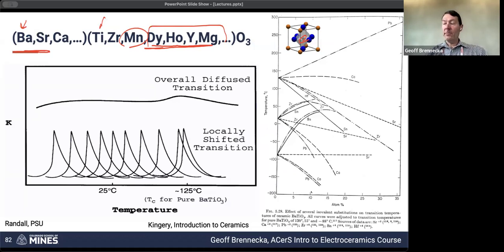And holmium and dysprosium happen to be right about in the middle. They're just as happy being in the A site or the B site, and so they can end up being self-compensating. If your sample has too many oxygen vacancies and needs to compensate for that, then maybe the holmium and dysprosium will hang out on the B site. If you've gotten your A site to B site ratios just a little bit off, these kinds of dopants can help compensate for that a little bit. So that's one of the thought processes that go into doping and alloying these barium titanate based materials for capacitors.